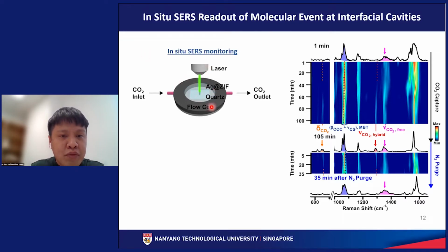Basically, we place our substrate inside a gas flow cell. So this gas flow cell got a quartz window, whereby laser or Raman scattered light can freely transmit across this quartz window for detection. So from one end, we will blow in CO2, carbon dioxide gas, and the other end will be the outlet. So this is the SERS spectrum that we get with continuous CO2 absorption.